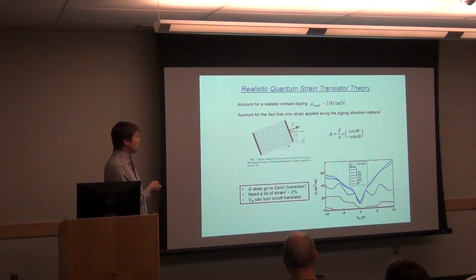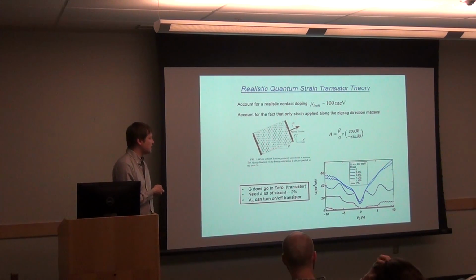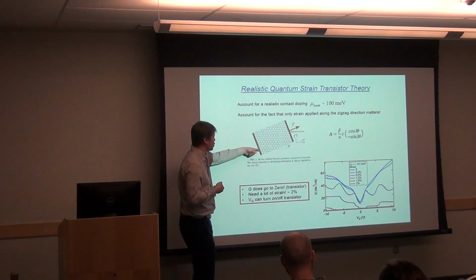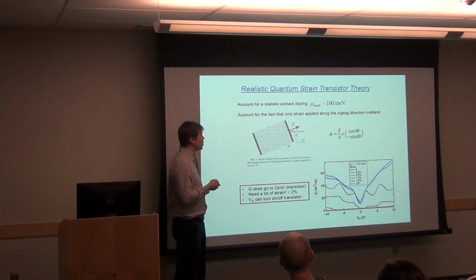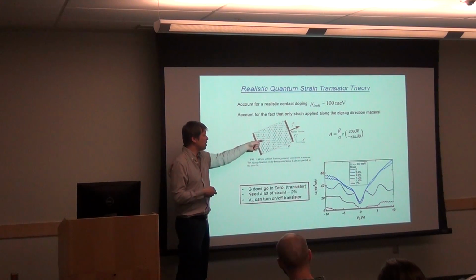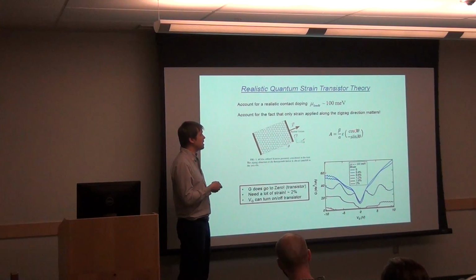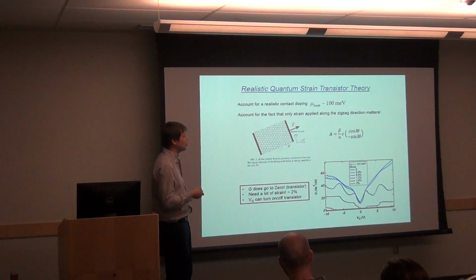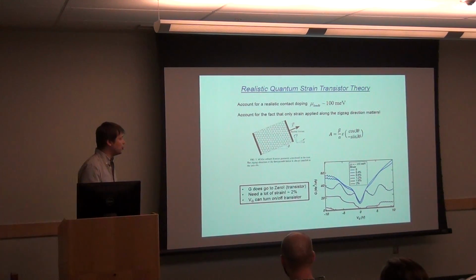So to really make a prediction as to what's going to happen with strain, that's the number we want to put into our theory. The other thing that was absent from the other models is that the angle of the strain matters, because only the strain along the zigzag direction of the graphene matters. Since in our experiments we don't control the orientation of the graphene, we can basically have a varying angle. So it can be, on average, a square root 2 over 2 effect, but we need to make multiple devices to see that.